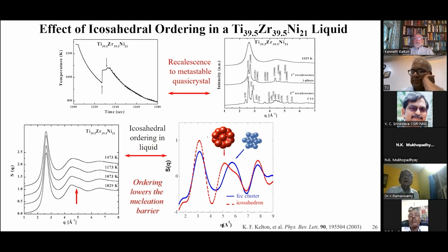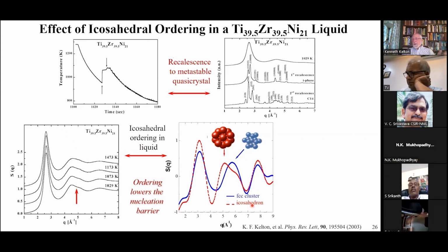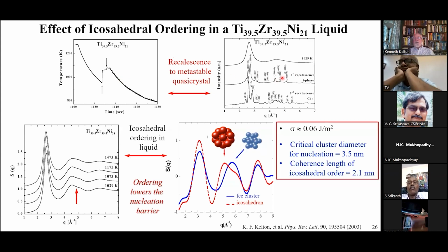If we look at any possible 12-fold local clusters, and I show it here for FCC and the icosahedron, but if you look at it for HCP, and we even looked at it for BCC, which is not 12 coordinated, what you find out is that the only cluster that gives rise to this shoulder that's developing is the icosahedral peak, or icosahedral cluster. So this is a signature of icosahedral ordering in the liquid, which I speculated could be the reason for the formation of the metastable icosahedral phase.